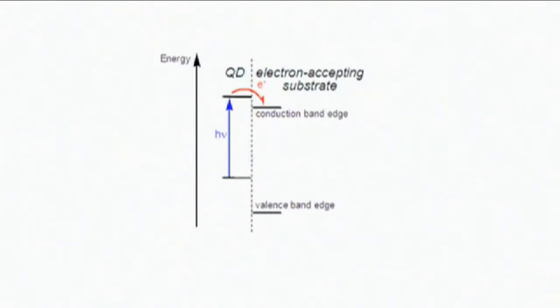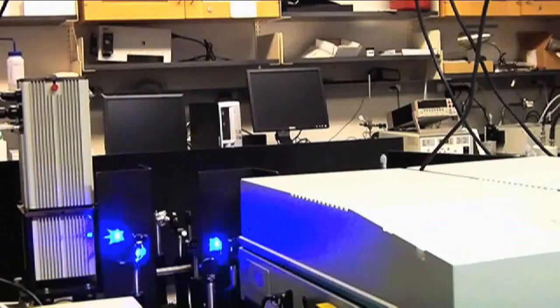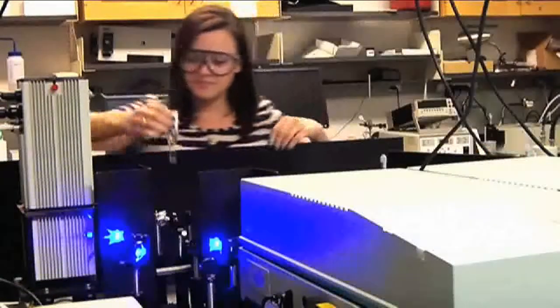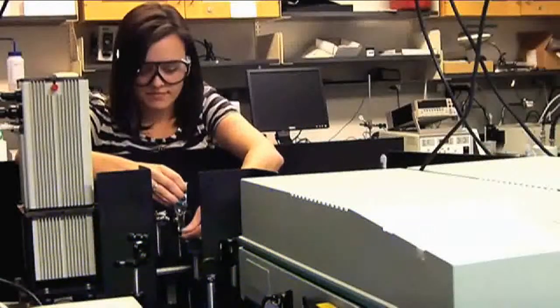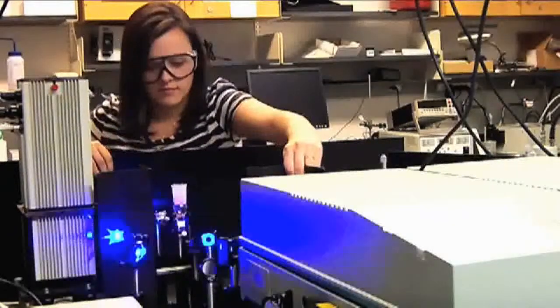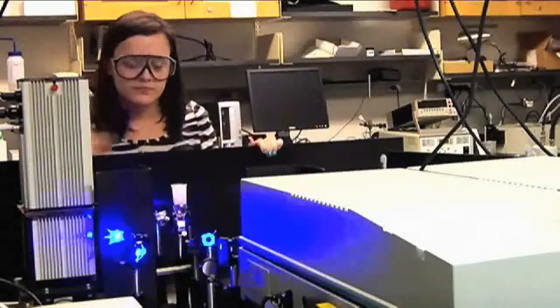Linker-assisted assembly is an attractive synthetic method because it probably offers maximal control over particle size and interfacial environment. Several groups have recently reported spectroscopic studies of photoinduced charge transfer at quantum dot substrate interfaces prepared by linker-assisted assembly. My research group uses steady-state and time-resolved spectroscopy to characterize such processes. Here, Casey Mulhern demonstrates the use of our nanosecond pulse laser. The laser pulse excites the excitonic or bandgap transition of quantum dots, and electron transfer processes are monitored by measuring transient absorbances and time-resolved emission signals.